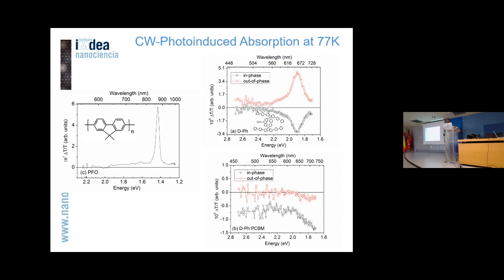Thank you. We know it's reversible, so the system comes back to the same state originally, so we know we are not modifying the system with the laser. We have proof that we don't have triplets, so we think the only interplay here comes from singlets and also from the polymer. The other thing I didn't mention is that the time frames we are looking at are restricted to only 200 picoseconds. Those are pretty short times for this kind of system.